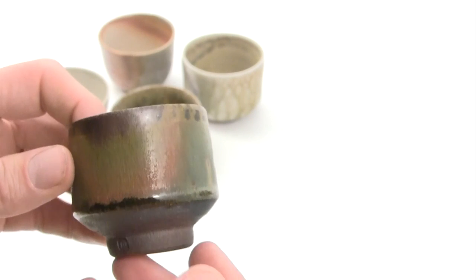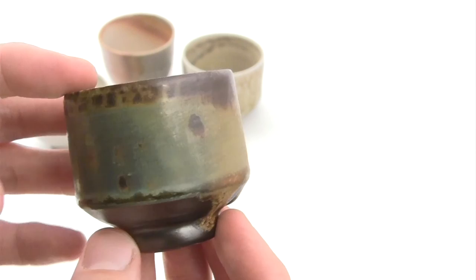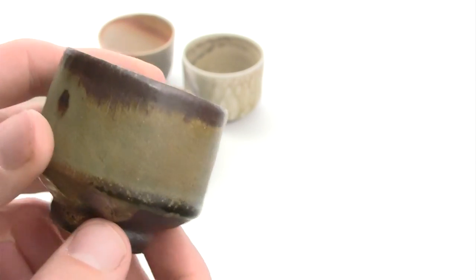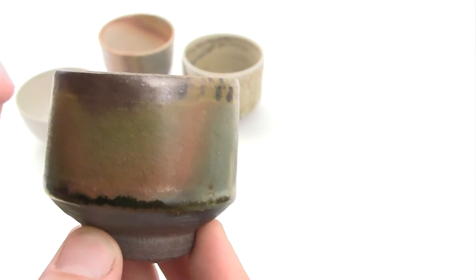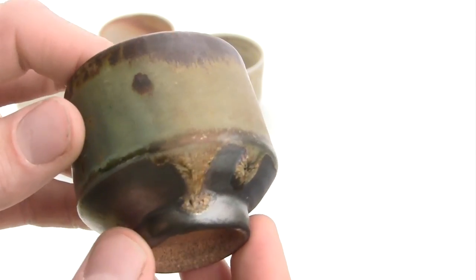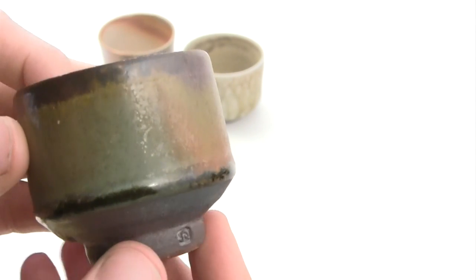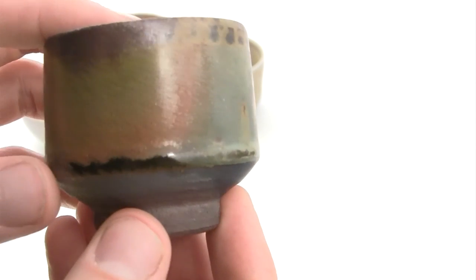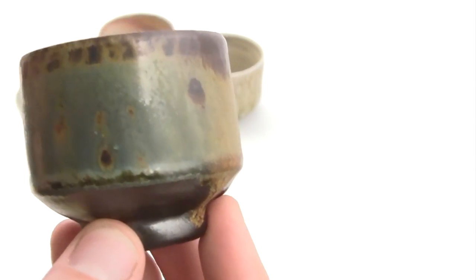This cup is a dark stoneware clay and on top of it a clear glaze. But since the dark clay has a lot of iron in it, during the firing process iron will bubble up into the glass and mix. And since the glass is moving at these temperatures, different thickness of the glass, different temperatures all the way around and different amounts of iron change the colouring of the pot. So iron in reduction can become all the colours of the rainbow, but in oxidation you'll have a hard time getting anything else but yellow. So these colours are all from the reduction part of the firing, even though re-oxidation is a part as well.